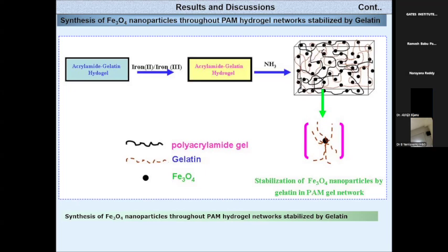Then into this polymer, we are injecting TEMED as well as ammonium persulfate solution into the monomer copolymer solution. Then we are slowly raising the temperature to 50 degrees C. There you will get some free radicals. Free radicals in the sense that the ammonium persulfate breaks down, thermolytic degradation takes place, so that the persulfate creates some free radicals. These free radicals will attack the acrylamide monomer chain.